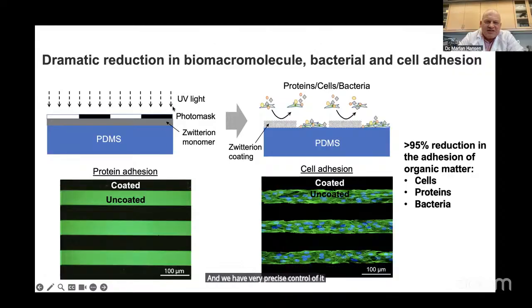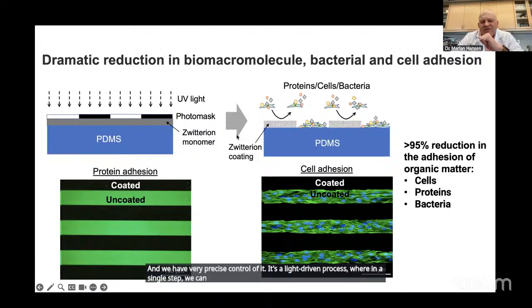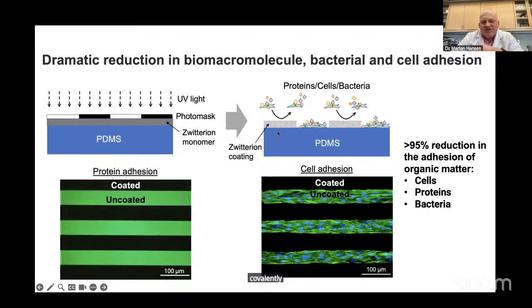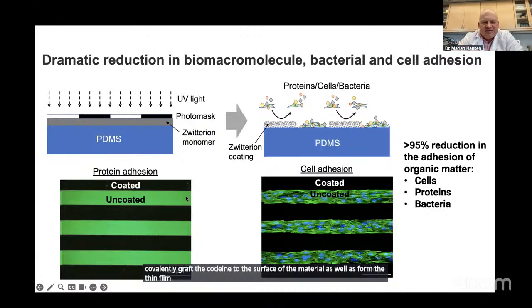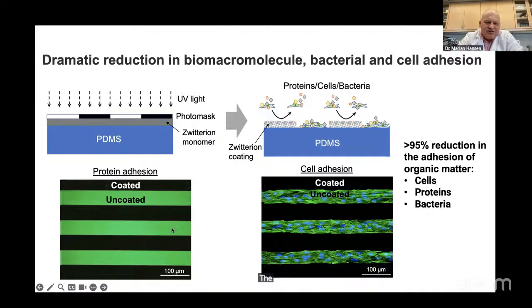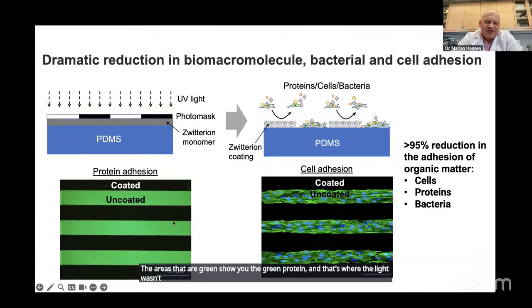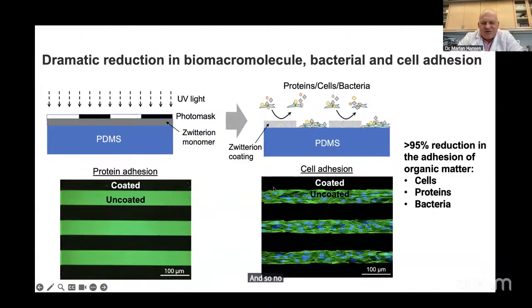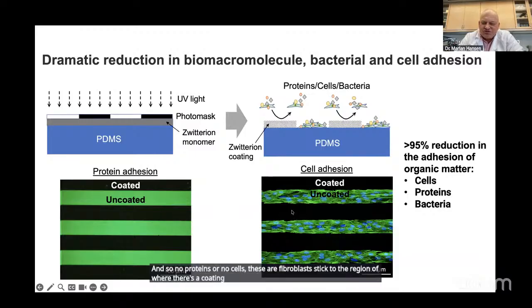It's a light-driven process where in a single step we can both covalently graft the coating to the surface of the material, as well as form the thin film. And by controlling where the light shines, you can see how effective it is. So here is a protein adhesion assay where the areas that are green show you the green protein, and that's where the light wasn't shined, and the areas that are black are where the light was shined, where the coating would exist. And so no proteins or cells, these are fibroblasts, stick to the region where there's a coating. And we can control that at a micro scale by controlling light.